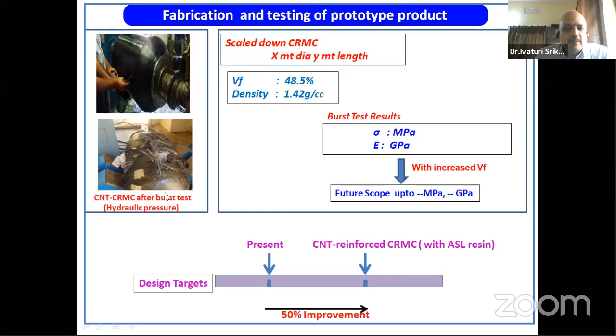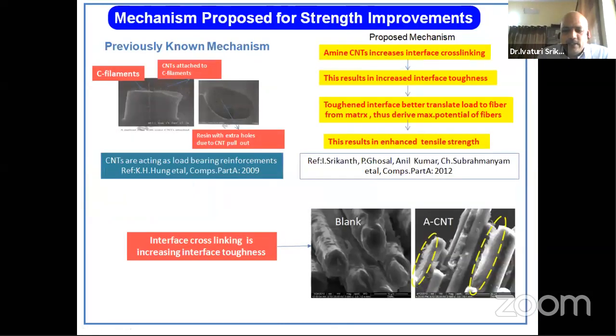So we have scaled down and realized CNT-added composite motor casings, and we have done the burst testing. We could get significant improvement compared to the conventional structure, but the improvements are mainly due to the resin system. Improvements due to the CNTs are very marginal, less than 10%. So what we proposed is,